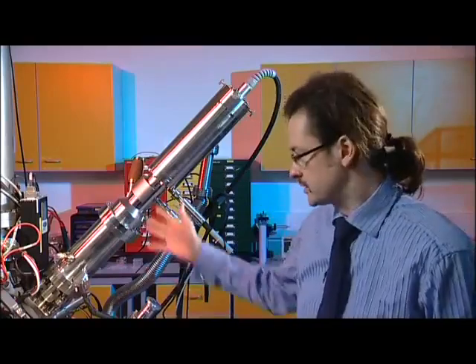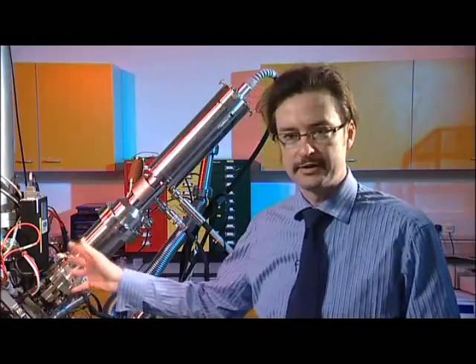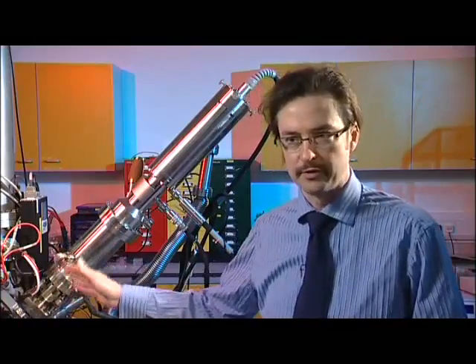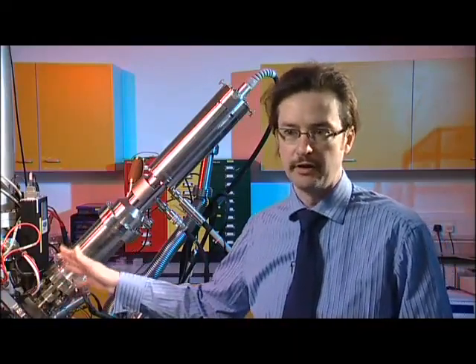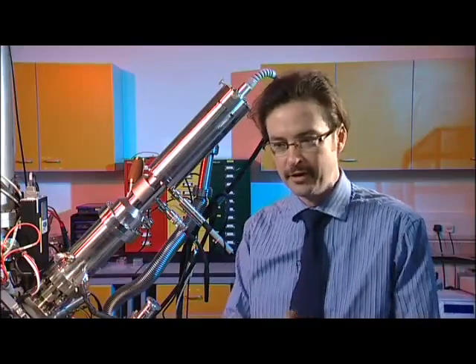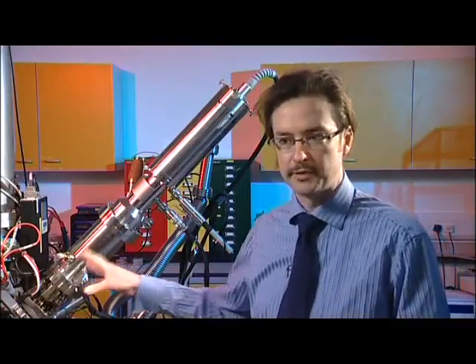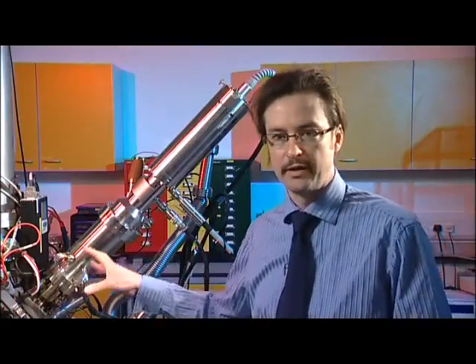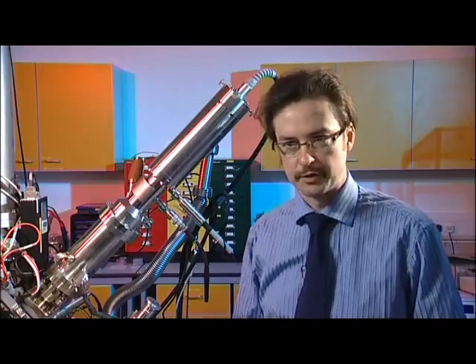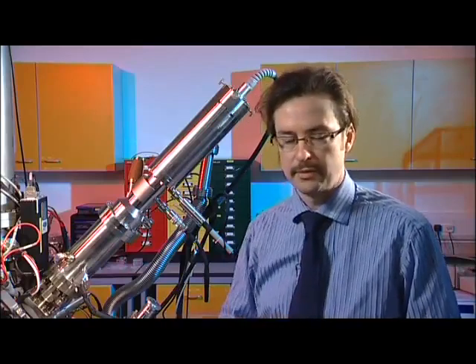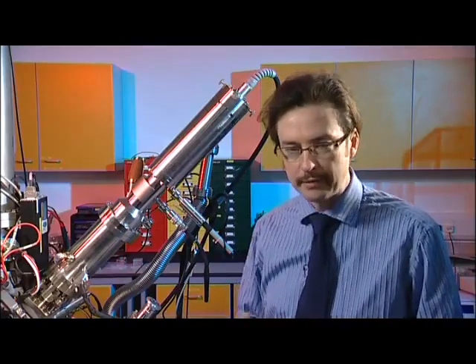We can use techniques like this secondary ion mass spectrometer to actually identify what the distribution of the particular chemical species are that are on the hair surface. And if you look at your shampoo bottle when you're at home, you'll see there are probably 20 to 30 different ingredients in that. And with techniques very powerful like this, we can actually localize where those individual components are. If we use techniques like X-ray photoelectron spectroscopy, we can very accurately measure the thickness of these molecular layers with about nanometer resolution on the surface of curved structures like fibers and also nanoparticles.